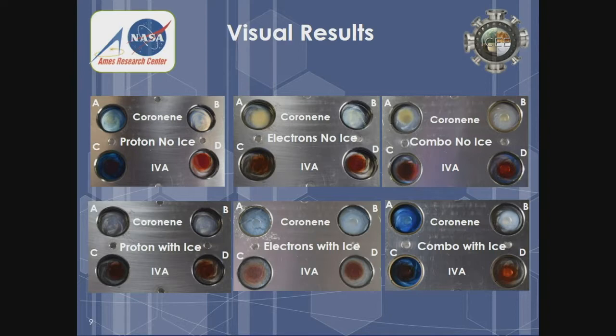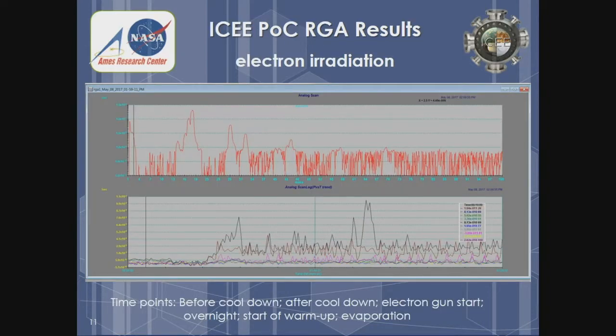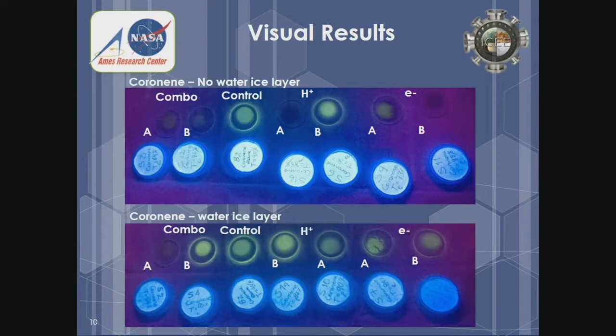Here are some visual results of what happened to the samples. This is the sample holder we made for the chamber — it was a huge chamber — and we did duplicate samples: coronene at the top, isoviolanthrene, or IVA at the bottom. You can actually see color changes in the coronene; it's a translucent material that changed color upon bombardment. The blue color you're seeing here is actually color centers developed in the salt windows during irradiation. A lot of PAHs fluoresce when you put them under UV light, and here's our control sample with no irradiation — it fluoresces great. The irradiated samples with no water ice layer, not so much. This tells us we're destroying the aromatic structure — we're actually changing and altering it.